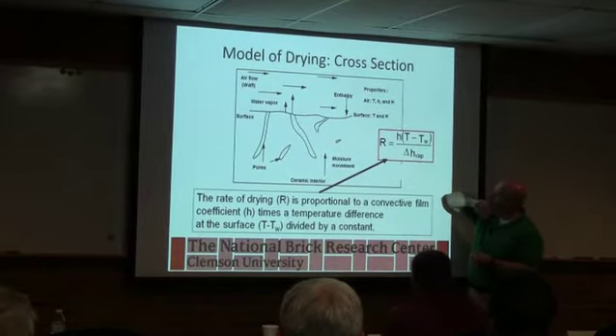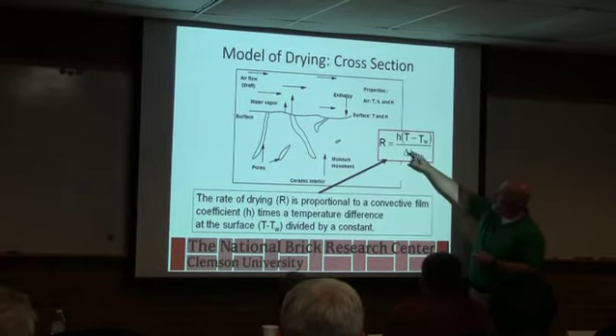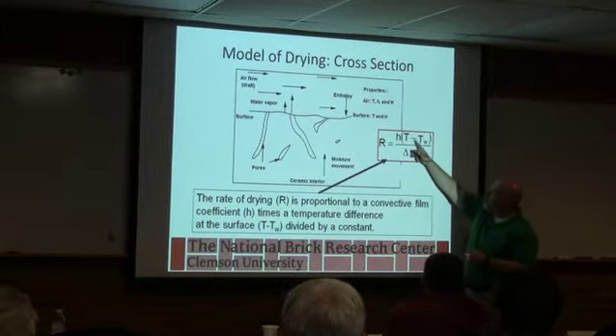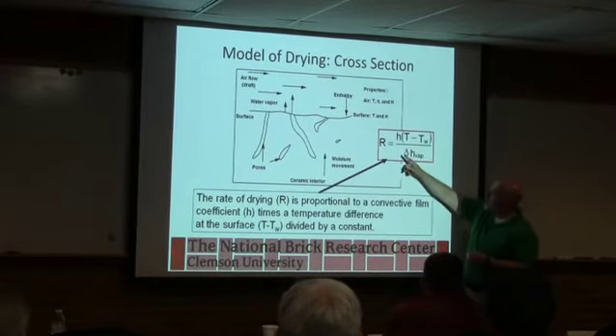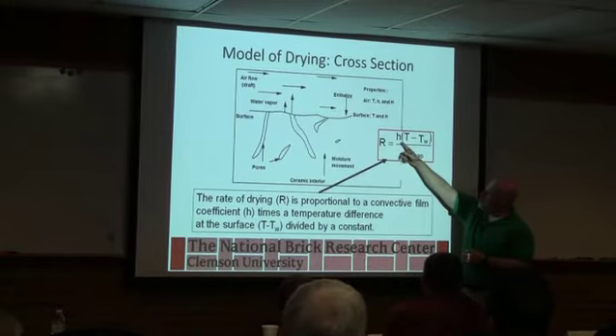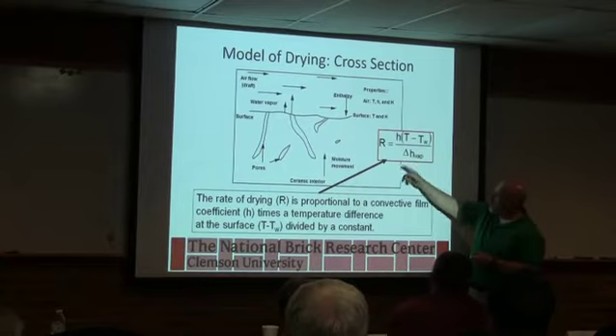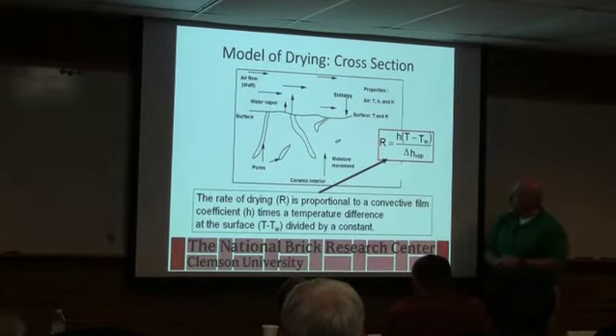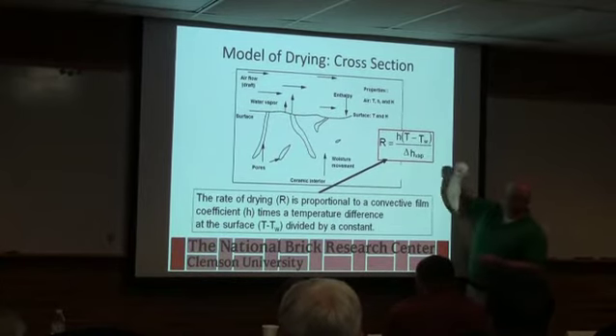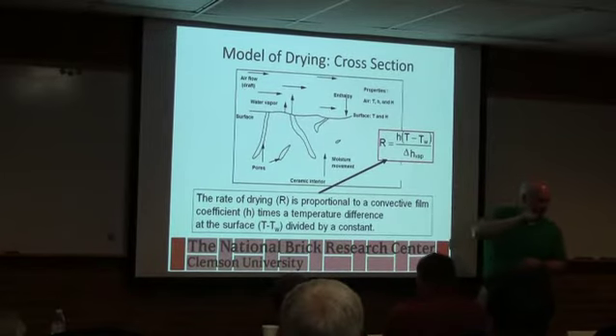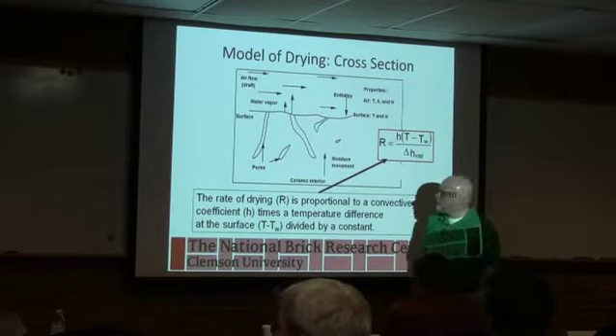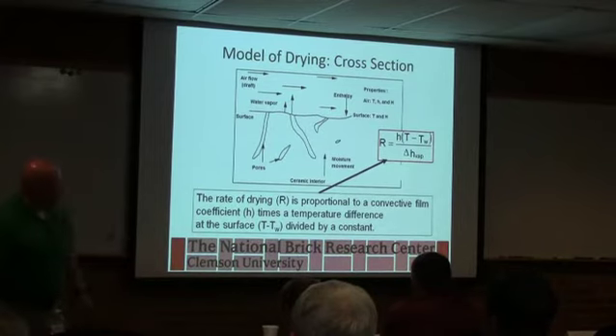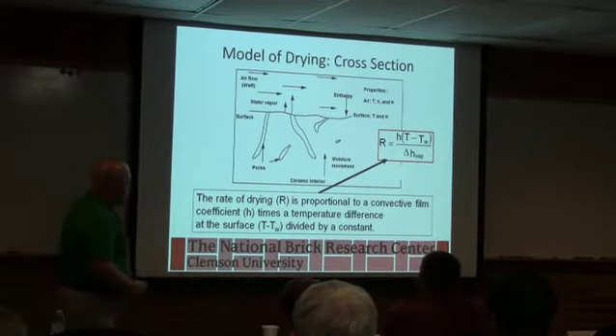So the rate of drying is proportional to the driving force, basically the humidity, the film coefficient, which has to do with the way the air interacts with the surface, and the evaporation rate. So in the past, we'd start pulling out psychrometric charts and reading points, but now that we have calculators, I just don't see the point in doing that anymore, because I can look up the properties of the air. So we'll talk a little bit about calculations we can do in a little while.